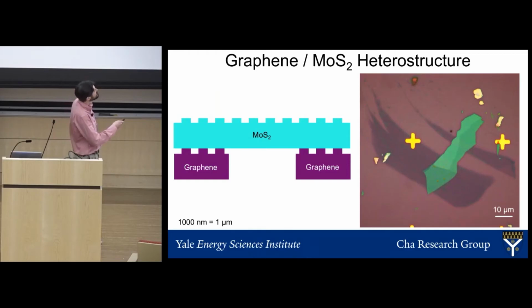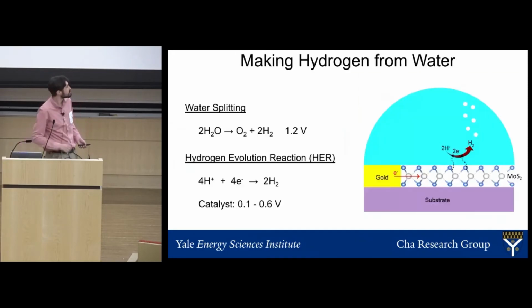What we see here, these two purple flakes are actually bilayer flakes of graphene. So there are two layers of graphene, so they're only 2 carbon atoms thick. And then this flake here is molybdenum disulfide, maybe 5 to 6 layers thick that I laid on top of them. So the way we actually use heterostructures in our lab is we try to make renewable fuels with them.